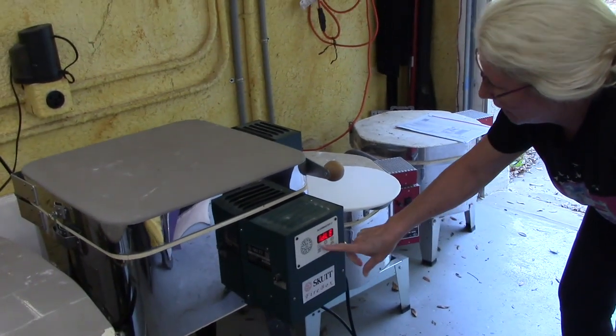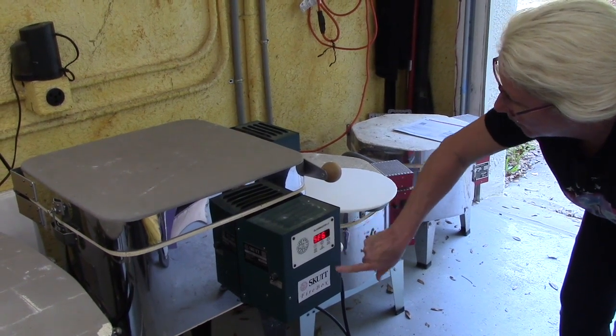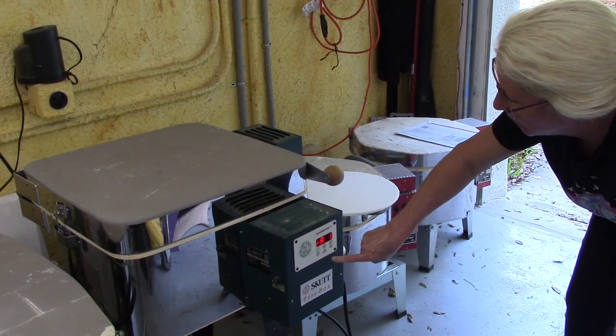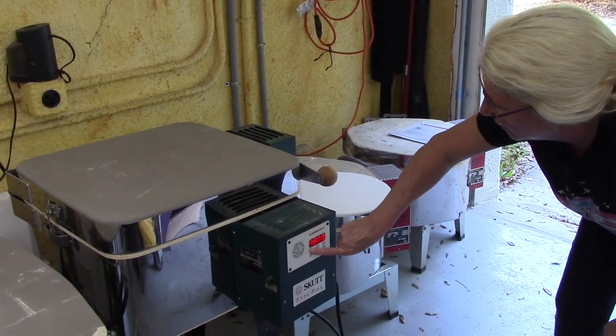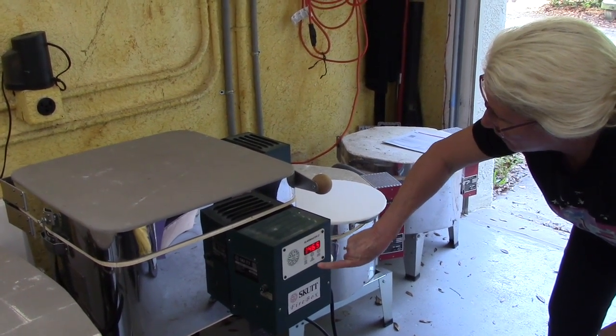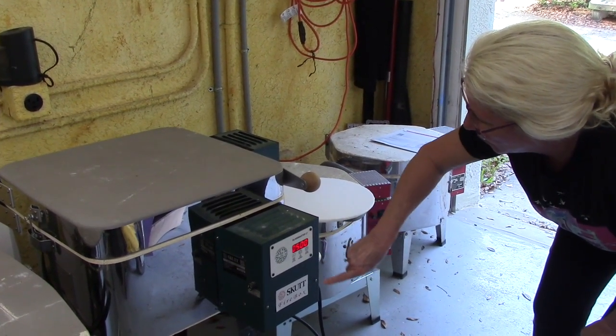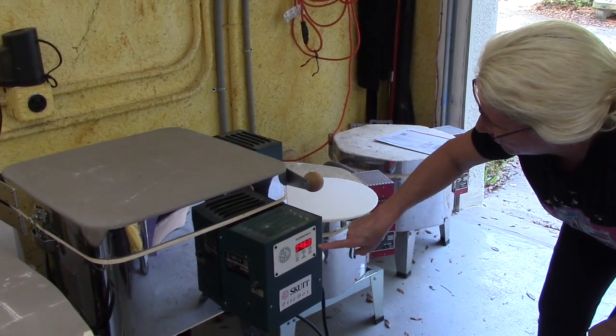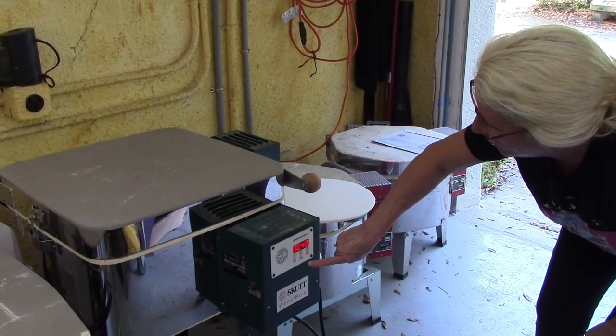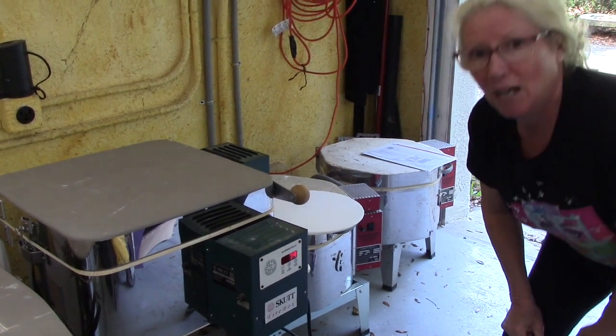I like to give everything a little bit of a blow and a kiss before I close it — fire well, my little beauties, I will see you soon. Over here, the kiln says it's at idle. Program number one — it has three segments. It's going to be a rate of 300 degrees an hour to 1300, hold for 40 minutes. Then a rate of 500 degrees to 1465 — that's our full fuse temperature — hold for 10 minutes. Then we go at a rate of 500 down to 960, our annealing temperature, and hold for 40 minutes. Now it's asking if we're ready, and we are. It's on and we are firing. A lot's going to be happening in this kiln overnight, so let's wait until we can open up and see what happens.